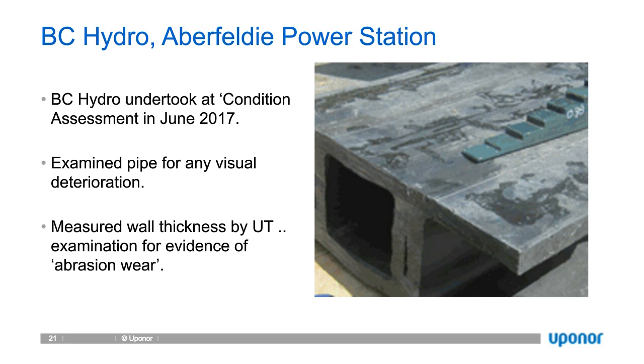The pipe that's shown in the sample here is not a sample of the Aberfeldie pipe. This is a standard regular Weholite portion. It was provided for this condition assessment to validate the accuracy of ultrasonic examination that BC Hydro was using as a means of checking for the remaining waterway wall thickness. They're trying to determine if there had been any wear on the pipe.